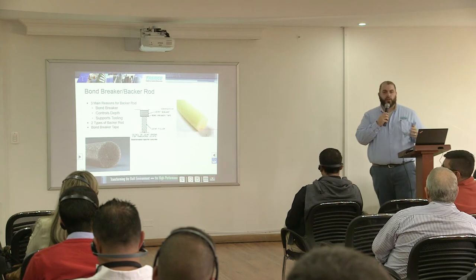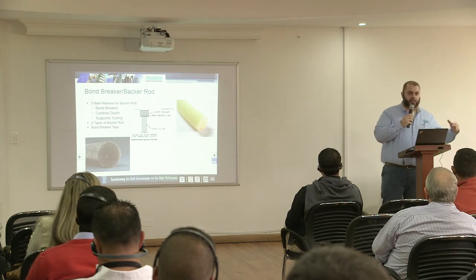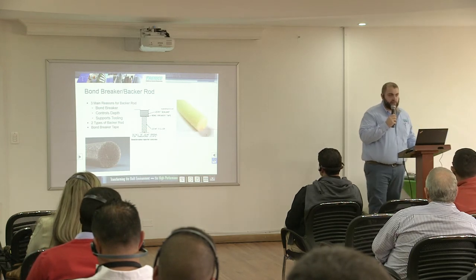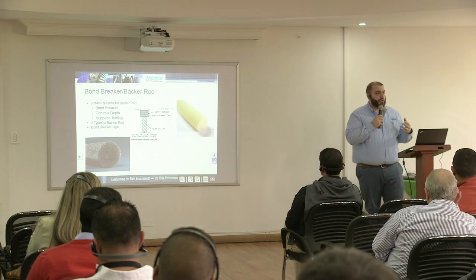The outgassing, what it is, it's when moisture comes into contact with some of the sealants, it releases CO2 and creates bubbles. That's not too bad of an example, but I've seen other examples where the bubbles are protruding from the joint and it just looks very unpleasing. So that's one of the benefits of using the closed cell backer rod, is you don't get moisture to the backside of that joint. As I said, typically you want to use the open cell in vertical joints above grade, and then the closed cell on horizontal joints on grade.